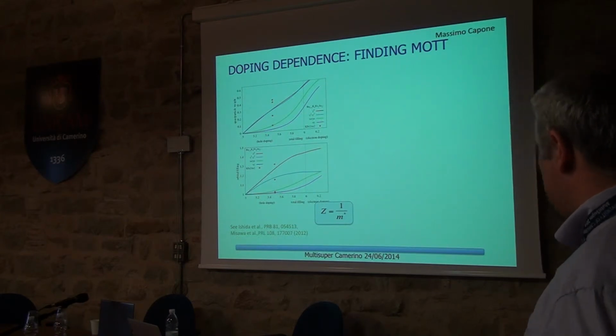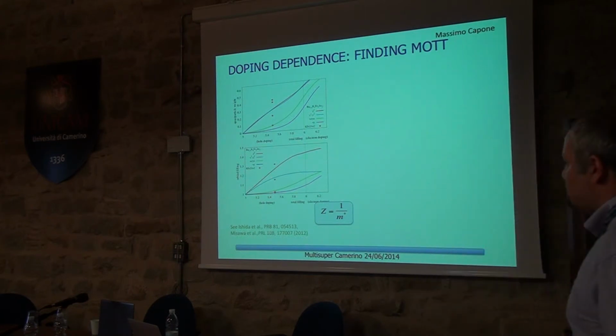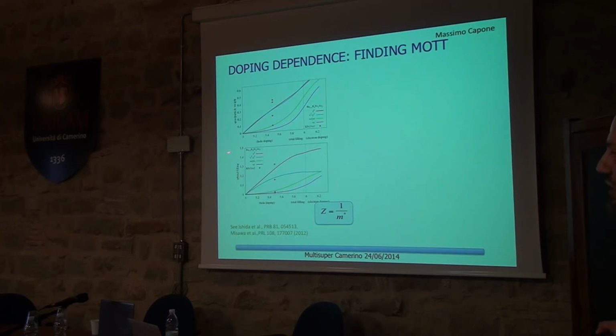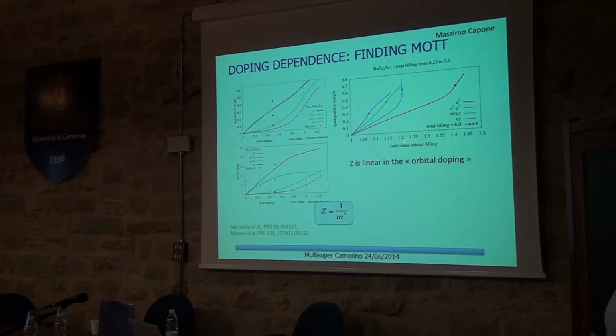Then one other thing is that I can play a nice game and plot the density of electrons per orbital in the same process. So this is how many electrons we have in the different orbitals, once again as a function of the same variable. We get some numbers, because the electrons can be wherever the chemistry tells they are, and of course it evolves as a function of correlations. The nice thing is that we can plot one as a function of the other. So now I'll plot this Z for an orbital as a function of the density for that orbital.